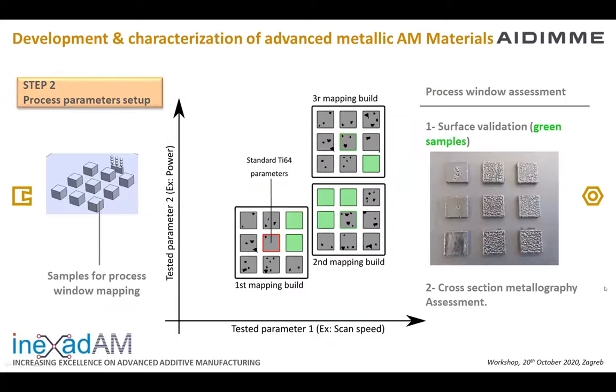How about the process parameter setup? It's usual to manufacture small cubes for the process parameter optimization. For example, keeping constant one parameter such as power, and modifying scan speed. In this way, you will obtain different cubes processed with different combinations of process parameters. Then these cubes will be characterized in terms of density, and we will obtain the correct window of process parameters.